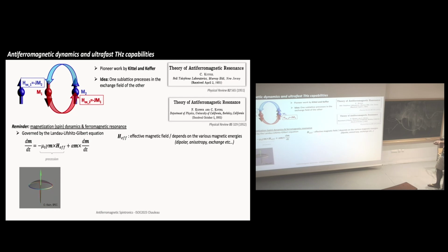So, the effective field can depend on a lot of different contributions: the dipolar field, anisotropy, exchange, and so on. Then, of course, you have a second term, because you will not precess like this forever. Then you will finally relax along the effective field. This is the damping term. And the damping term can also be important, but we will discuss that a bit later.